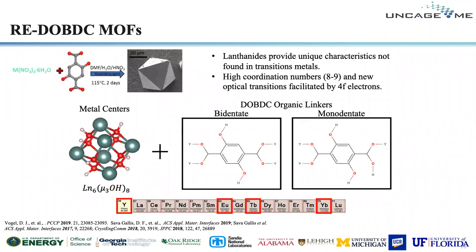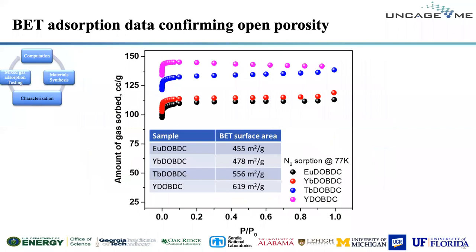In these metal clusters with transition metals, you can have a bidentate configuration where the dangling oxygen off the linker binds to the metal, or one that is not binding, providing stability in the metal cluster. We generally look at europium, terbium, and ytterbium as benchmarks, plus yttrium, which acts like a lanthanide but is not. Our BET absorption data shows that no matter which element we use, we end up with a high porosity open framework, meaning we're forming our 3D network.